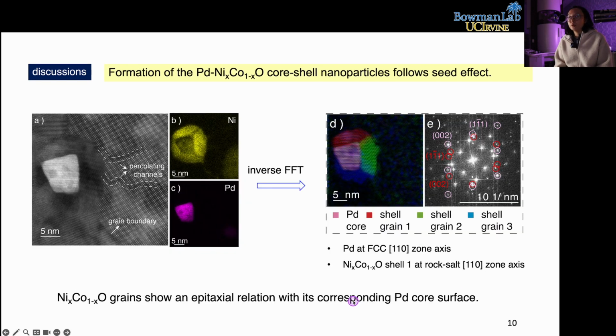Then we will decipher the formation mechanism of this palladium nickel cobalt oxide core-shell nanoparticles. We make a STEM high-resolution image to track atoms inside the palladium core and the nickel cobalt oxide shell. From this image, you can also see the shell part is made of about 3 grains.